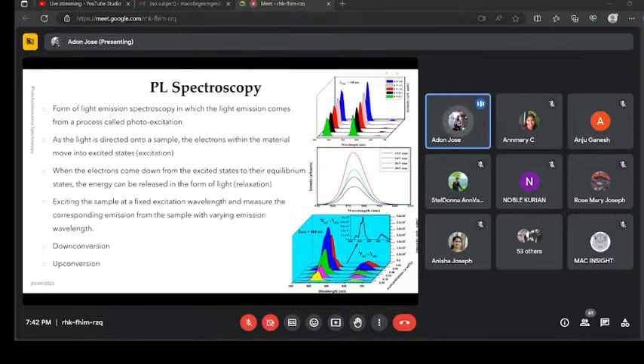Whenever we are recording these luminescence spectra, there are two different types of processes we can consider. The first is down conversion, and the second is up conversion. The pictures that I have shown are results published in certain journals. In the first case, the excitation wavelength is of the order of 348 nanometers, and the emission we have recorded is in the range from 450 to 700 nanometers. That means we provided greater energy and observed only lesser energy. That is usually the case.